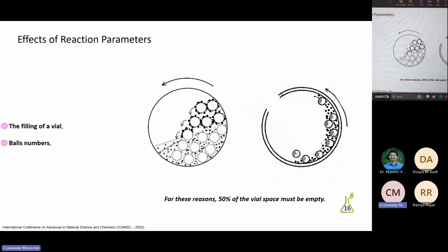The filling ratio of the vial is another significant parameter due to the need for enough space for moving freely in the container. When the amounts of balls and powders have been small, the production rate has also been small. If the amounts are large, there are not enough gaps to move and the energy effect is much less. For this reason, 50% of the vial space must be empty.